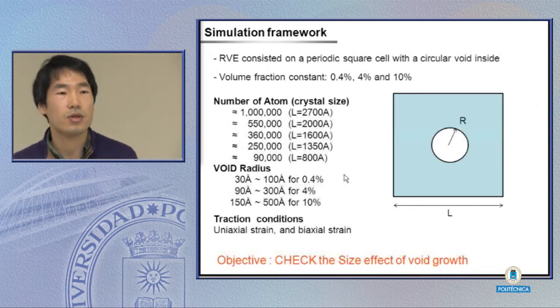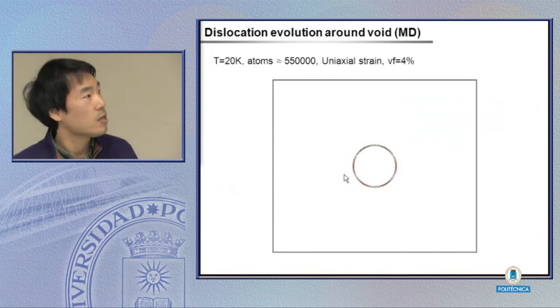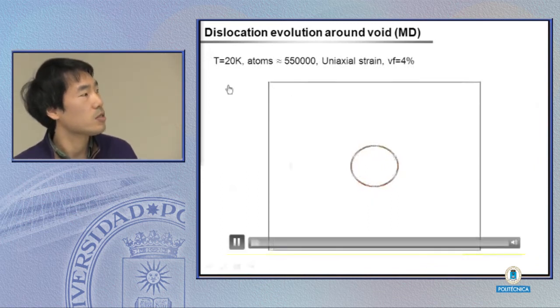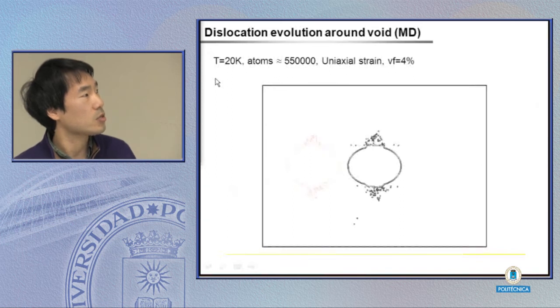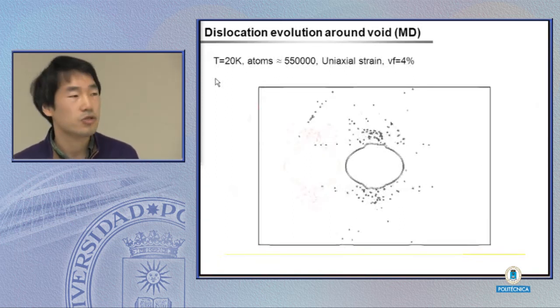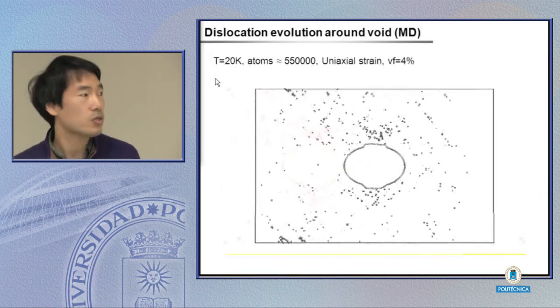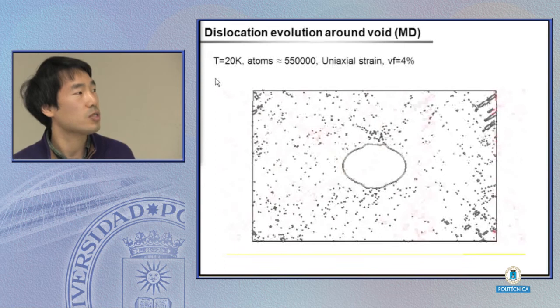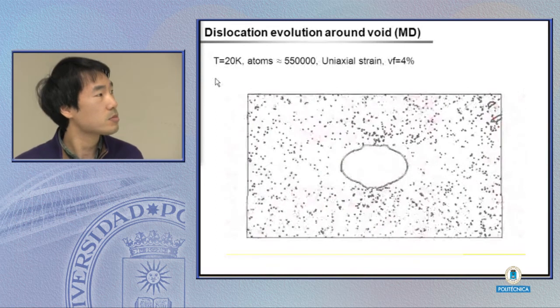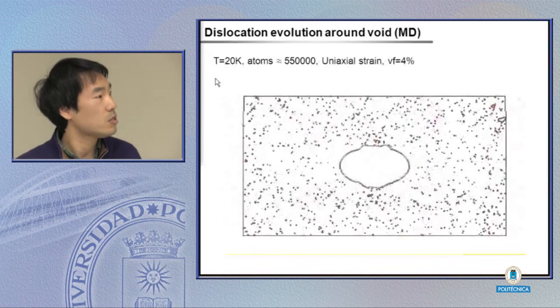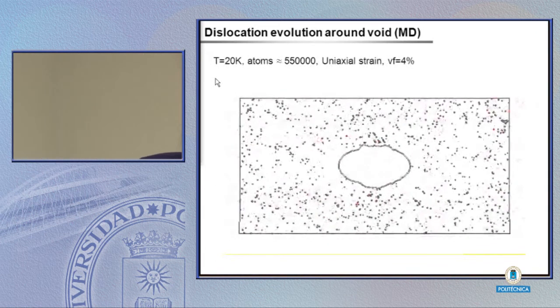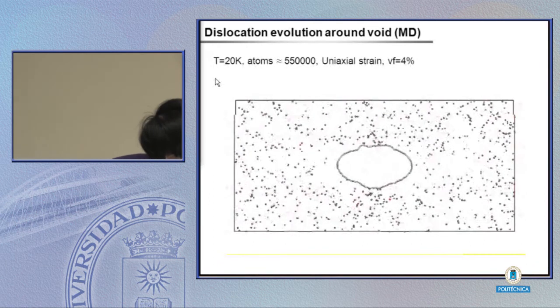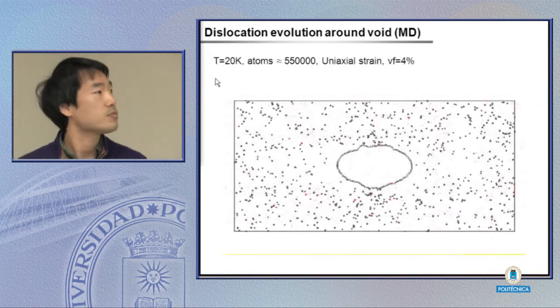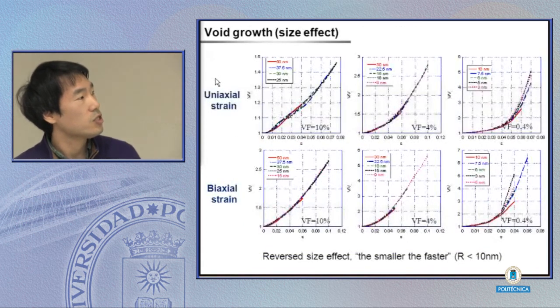And here is the system of what we are doing with the molecular dynamics. We have the crystal, which has several sizes, and the voids. And the void size is controlled by the volume fraction. Using this simulation, we check the size effect of the void growth and the dislocation evolution around the voids. Here's one result, the dislocation evolution. As you can see, the dislocations are generated at the surface of the void and evolved like this.